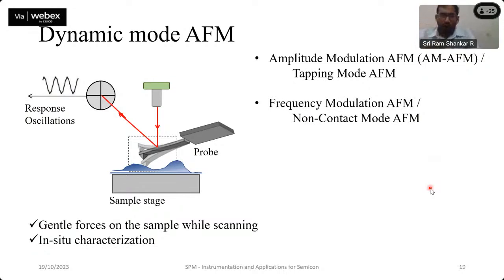Okay, so in order to avoid this particular drawback of the contact mode AFM, wherein you need to be very careful about the forces that you are applying, and then if your sample is loosely fixed to the substrate, what can happen is you can drag away some of the sample along with the tip. For example, if you have a DNA strand just kept on a substrate, and you are using this contact mode AFM to characterize this DNA strand, then as soon as you start scanning, it will scoop away the DNA strand along with the tip. We don't want such an accident to happen.